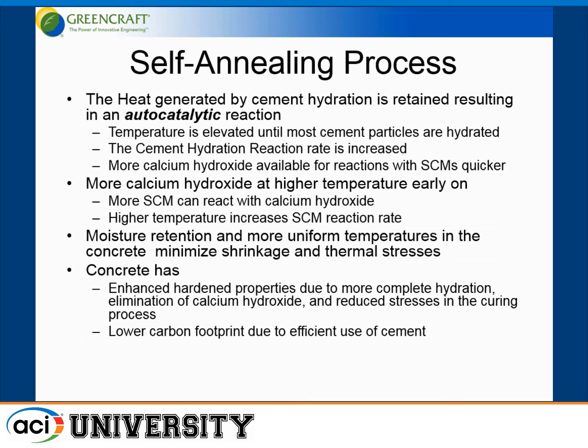So another way to describe the self-annealing process is by looking at the heat generated by the cement hydration retained in the formwork to create an autocatalytic reaction where the temperature is elevated and maintained until most of the cement particles are hydrated, and this causes the cement hydration reaction rate to increase, which in turn will create more calcium hydroxide available for reacting with SCMs quicker.